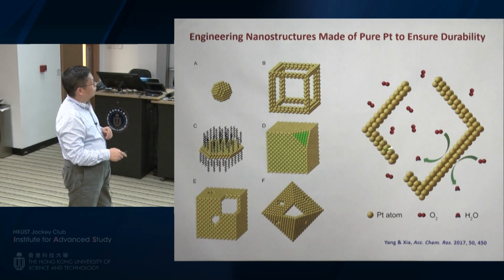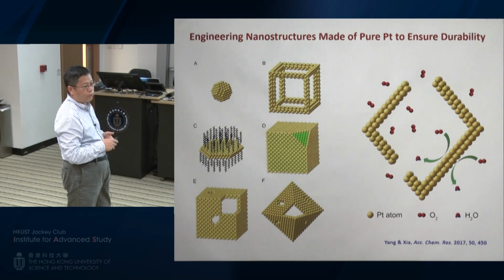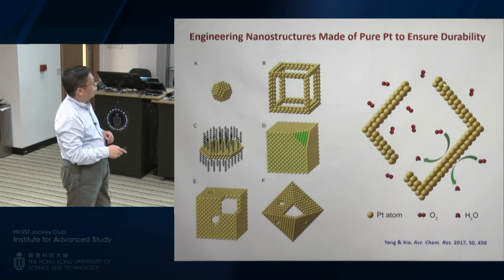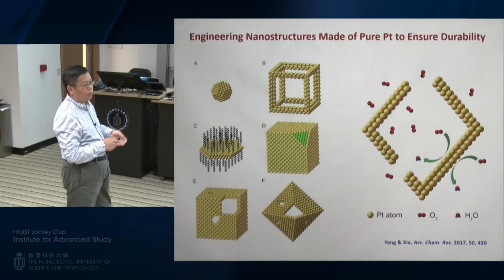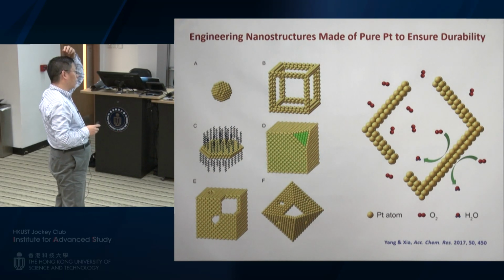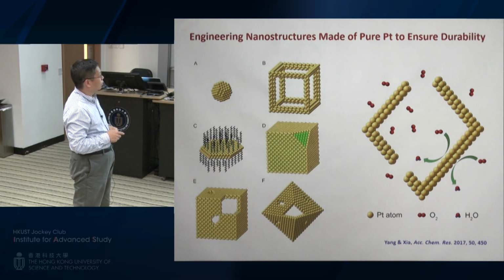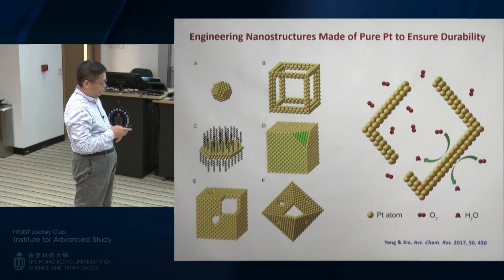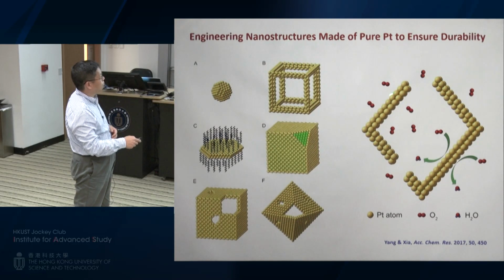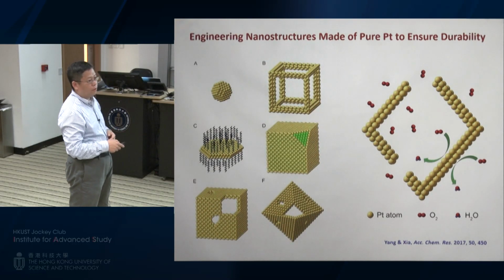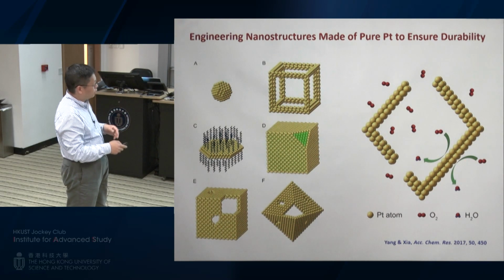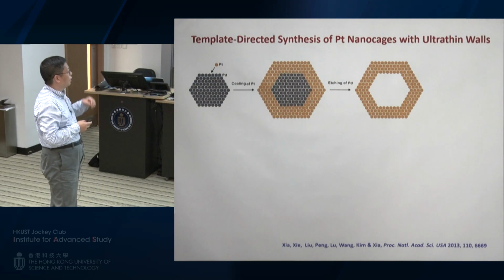And in the future, maybe they should become the choice for the catalyst. If it's only 2 atomic layers, and both inner surface and outer surface can participate in the reaction, essentially you don't waste any platinum atoms, so you are going to have the highest possible utilization efficiency for atoms. And you can have a 111 facet on both sides. You can have a high specific activity. So combined together, it looks like you can get a platinum-based catalyst with high activity and good durability, because this structure could be made as big as 10s or even 20s of nanometers. It doesn't matter, because essentially all the atoms are going to be located on the surface. So that's basically the idea.